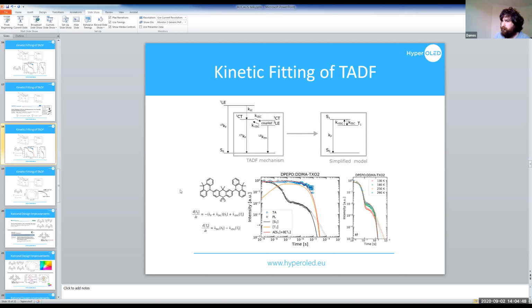It's still part of the process, but when you measure phosphorescence, you sometimes get the triplet energy of the auxiliary triplet rather than the one that's doing the coupling. As a result, you get a singlet triplet gap that is not necessarily representative of the RISC that you would measure otherwise. Okay, thanks for clarifying that.